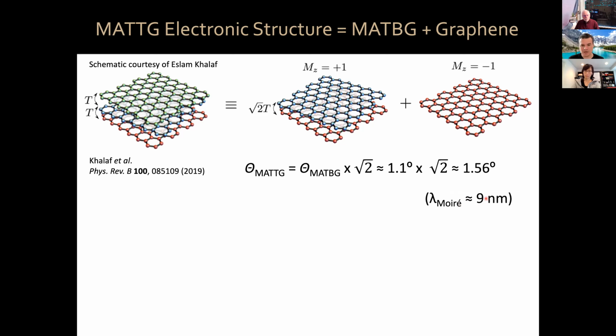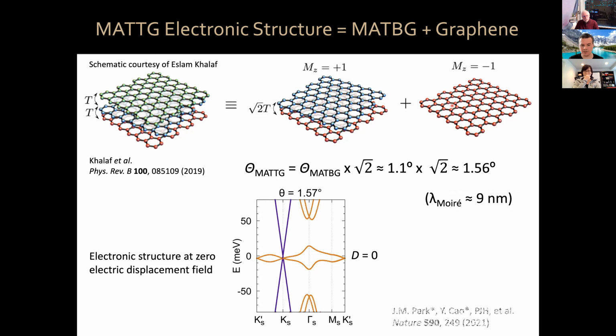Now, again, this trilayer electronic structure is bilayer graphene-like electronic structure plus monolayer graphene. Here you have it. When you do not apply a perpendicular electric field, so under mirror symmetric conditions, then your energy versus momentum has this orange flat band, which is a magic angle twisted bilayer graphene-like flat band, and then it has this massless Dirac dispersion characteristic of graphene, and these two are orthogonal, these states at zero displacement field.